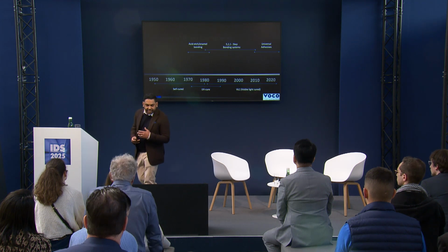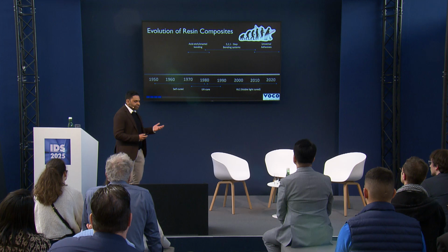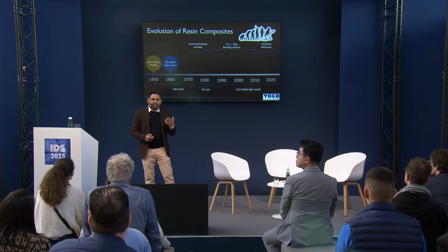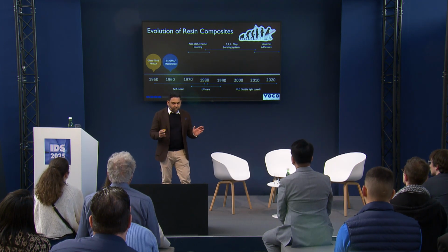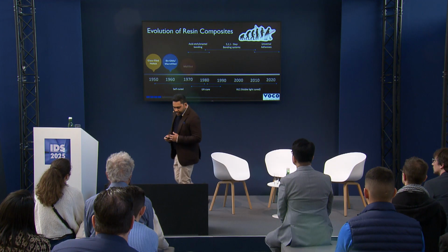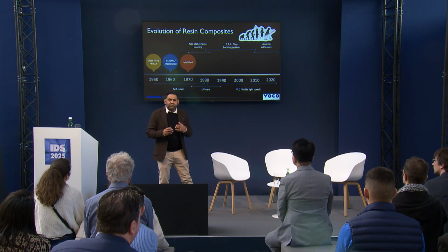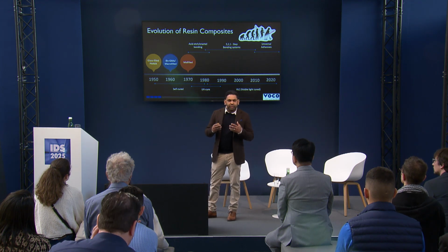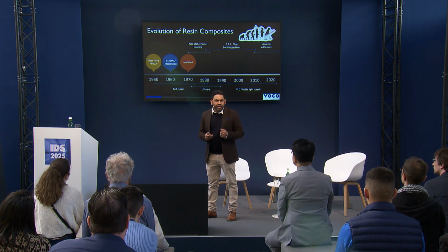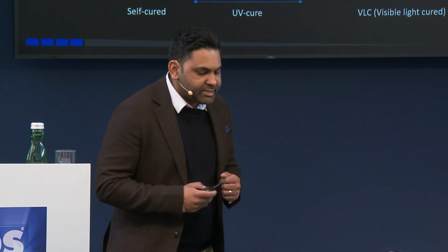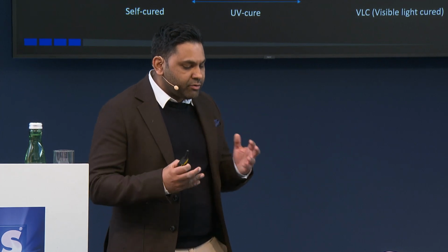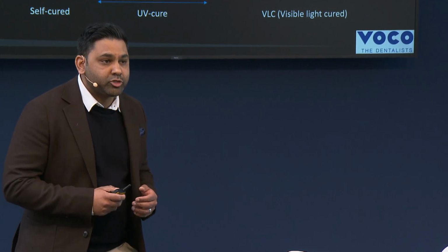Okay, so you've seen my office, and I thought I'll introduce the topic with a little bit of the evolution of resin composites. So, we've come so far, and where did we start? Essentially, in the 50s and 60s, we tended to see glass-filled PMMA-based resins and BIS-GMA macro-filled. This was the advent of the material, and the first version was often self-cured, so it was in need of much improvement. As we moved into the 70s, we started to understand that having more highly filled and macro-filled restorations of between 0 to 5 microns filler particles did give us many advantageous properties, and this is where we started to see an evolution of the material as acid etching and enamel technology also began to improve.